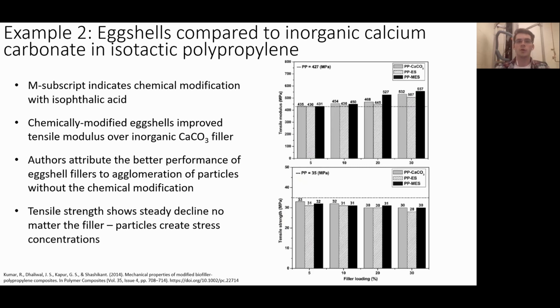So in the second paper I want to look at here, the authors did something very similar, but for polypropylene, which is a thermoplastic. So they did a chemical modification with isophthalic acid, and they noticed that the chemically modified eggshell composites had an improved tensile modulus over the inorganic calcium carbonate filler. The authors actually attributed this to less agglomeration of particles that had the chemical modification.